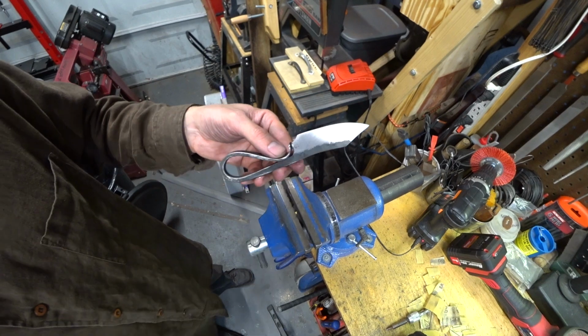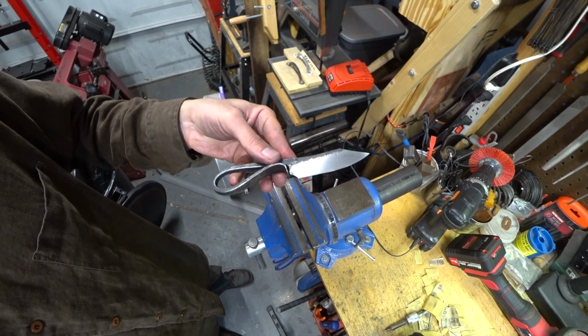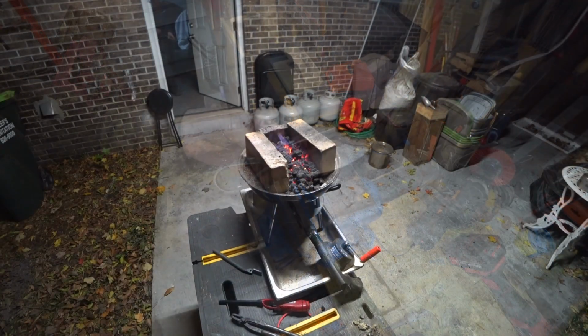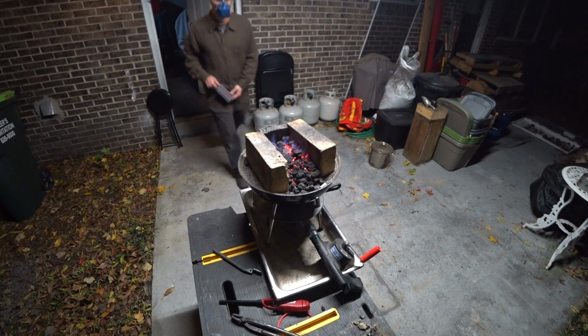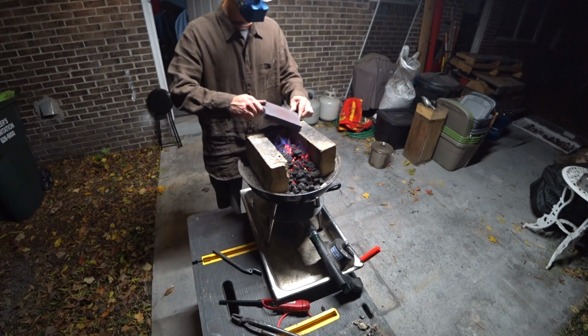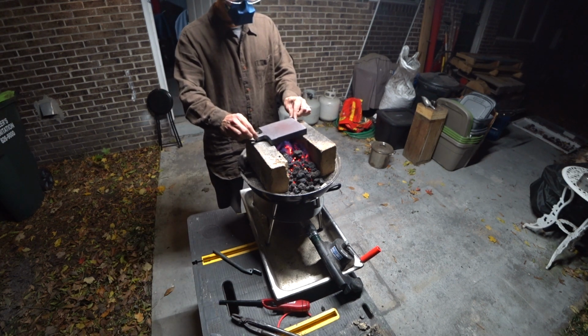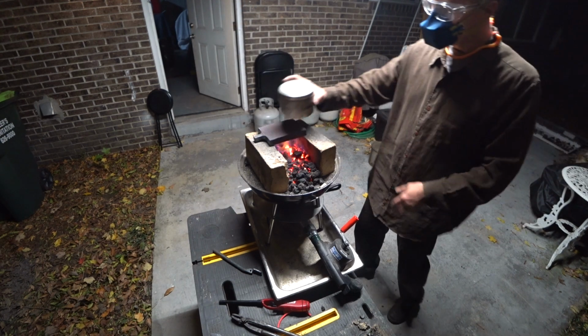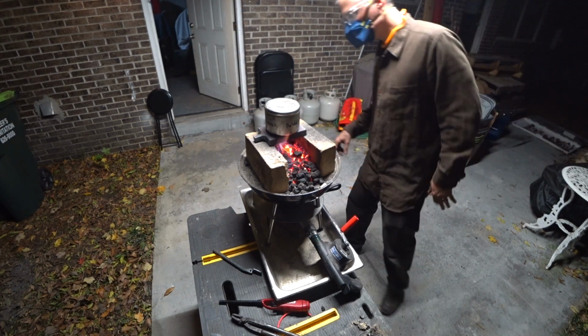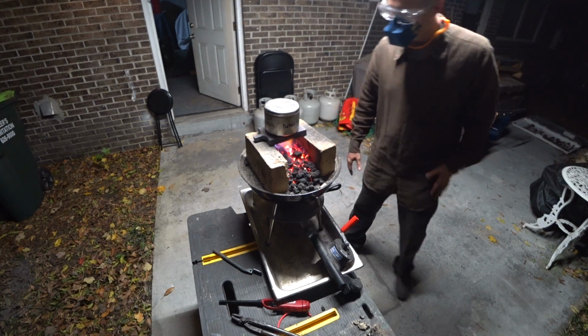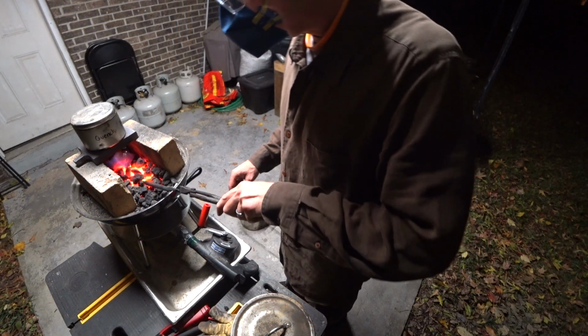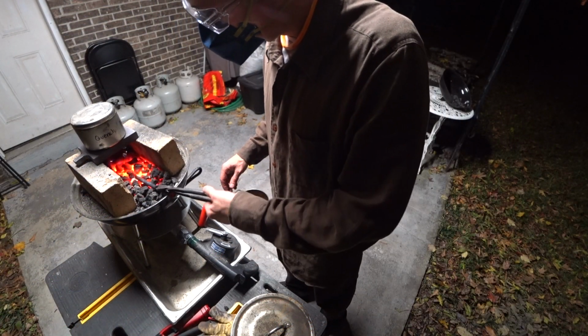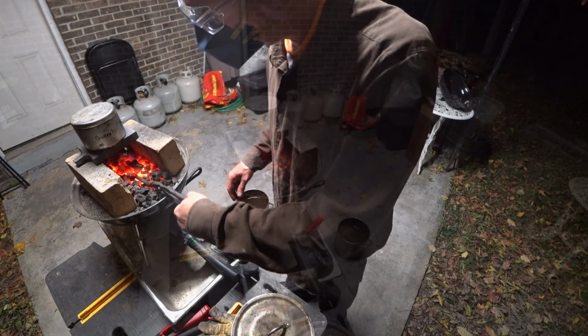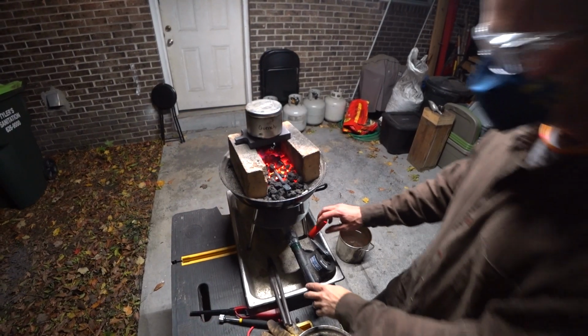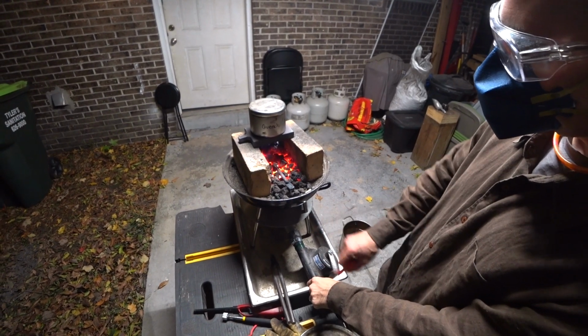So now everything is finished to a reasonable degree, and we're going to go ahead and do the heat treatment. So you can see I already have a nice fire built up with a bank of coals, and then I'm going to take a steel block and just set it up over the fire along with the quenchant. This quenchant is just a mixture of paraffin wax and vegetable oil so that it stays solid until you warm it up a little bit.